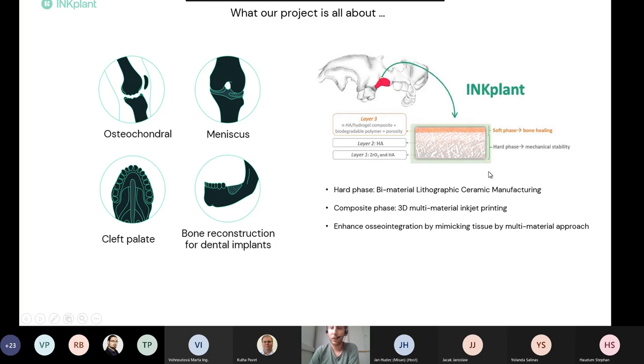for such a problem. We propose that an implant to tackle this challenge should consist of two different phases, also manufactured by two different additive manufacturing techniques. We call them the hard phase and the soft phase. The hard phase should provide the right mechanical performance of bone tissue and consists of two different ceramics. For example, this could be an interconnected lattice structure of hydroxyapatite and zirconia. And on top of this ceramic part, we aim to use inkjet printing to fabricate a biomimetic soft phase, a biomimetic coating, so to say.